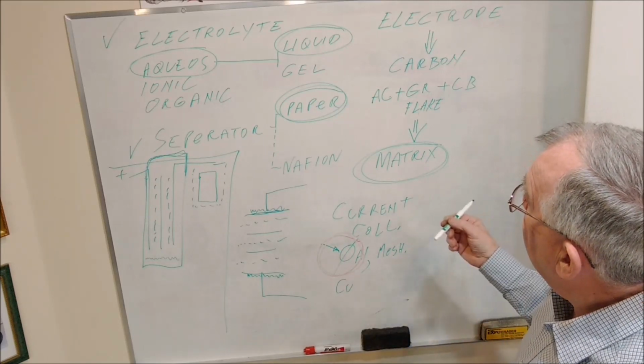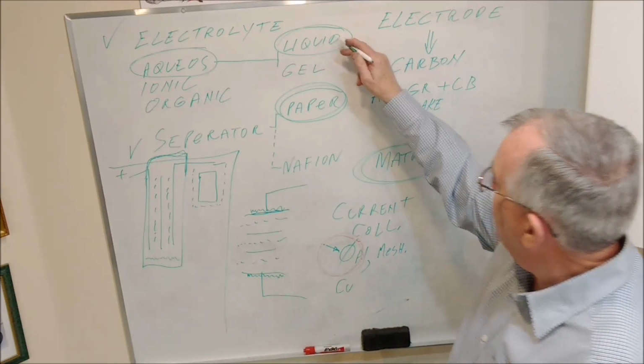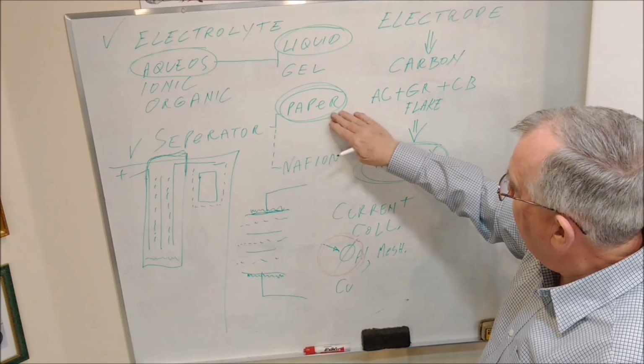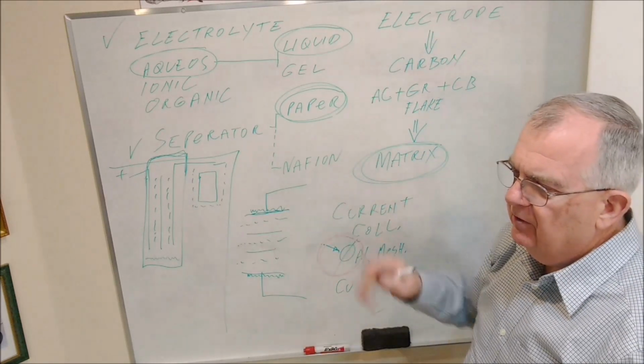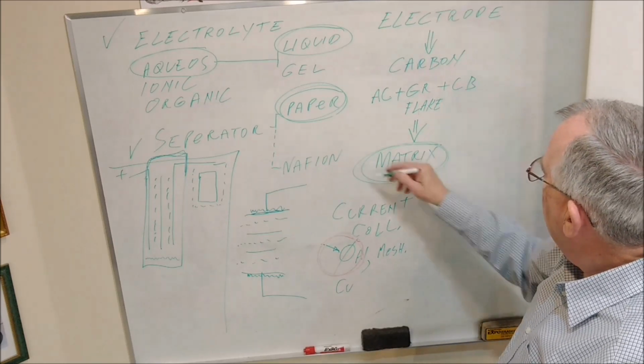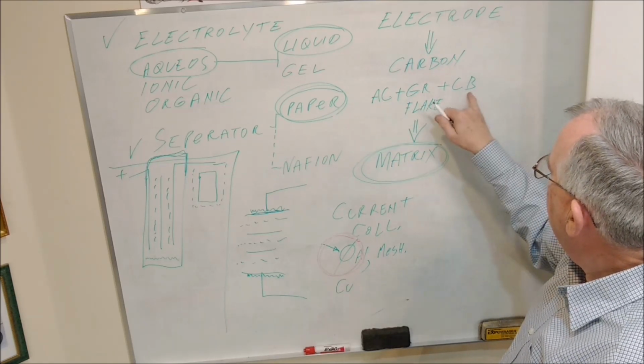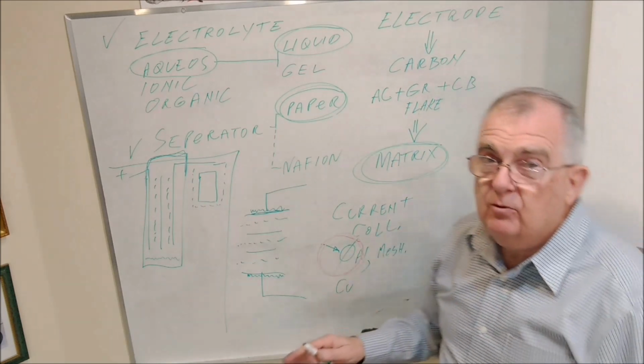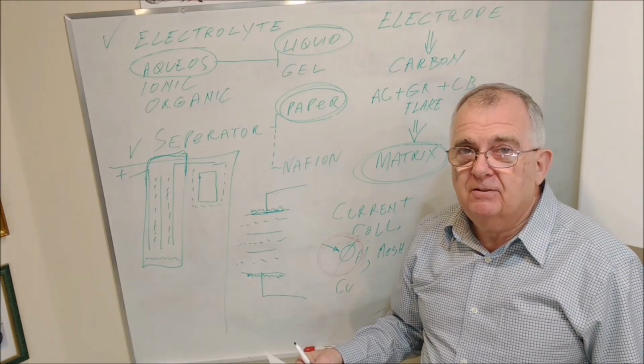And so far, just to summarize, we're going to be using something like a zinc sulfate aqueous electrolyte. Probably I'll stick for now with my 2 layers of copy paper for the separator. Don't get a lot of life out of this, but I'll get 10-20 cycles, at least enough to quantify things. And recently we've been playing with a composite or combination of carbons here. Again, fairly low cost, readily available. So that's where we're at on the roadmap, if you will, for energy storage.